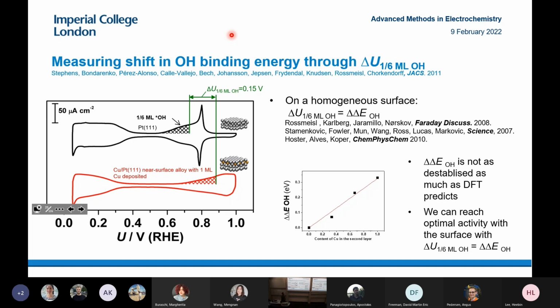I think the nice thing when you have a single crystal surface is that it's very homogeneous, and you probably only have one type of OH, that's what we're hoping. This is difficult to do in a nanoparticle, because then you might have several different kinds of OH and several different crystal orientations. Well, you could hope that it would apply. That's why I think it's always nice to do the work. To understand things, sometimes it's good to do it in a single crystal, because it should be comparable to a DFT calculation. Other surfaces could, in principle, work quite well. This is what we've been doing with Sylvia, for example, looking at a single atom catalyst, which is also quite well defined.